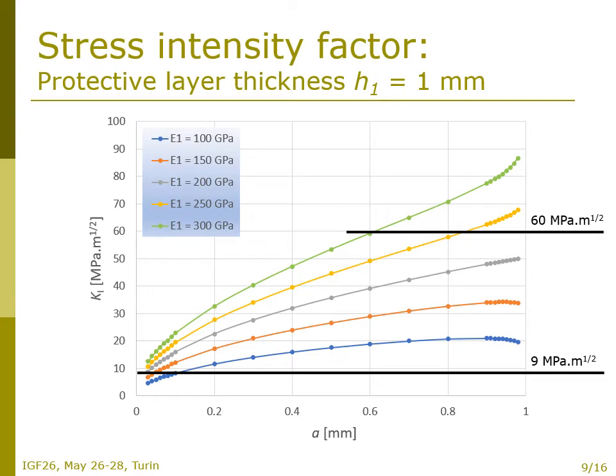Now this figure shows already the results of the pilot numerical simulations, particularly the dependence of the stress intensity factor on the crack length for different values of the modulus of elasticity of the layer material can be seen. Note that the gray curve represents the case of the homogeneous material because the Young's moduli of both materials have the same value. It means 200 gigapascals. This result corresponds to the 1 millimeter thin surface layer.